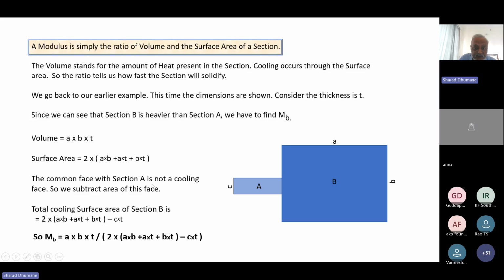Now the common face with section A is not a cooling face. When section A is connected to section B, this particular surface contact area is not really cooling. So we reduce this area from the cooling area. This is the cooling area, so we subtract this particular area, which is C into T. C is the thickness or width of this, and T is the thickness. So C into T is the area which is common. This is non-cooling area, so we reduce this from the total cooling area. So our modulus is A into B into T divided by the surface area minus the non-cooling area.